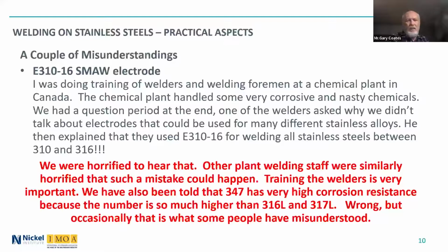Something similar, and I've seen it a few times, is that we've been told that an alloy such as 347 has very high corrosion resistance, and they believe it is true because the number is higher than 316L, 317L. And you can sort of understand where that's coming from: 316L is a higher number than 304L, usually more corrosion resistant. 317L is a higher number than 316L, more corrosion resistance. But it's, of course, completely wrong. And we've seen this both in North America and in Europe.